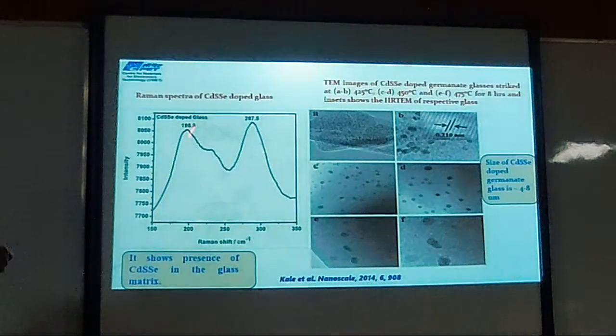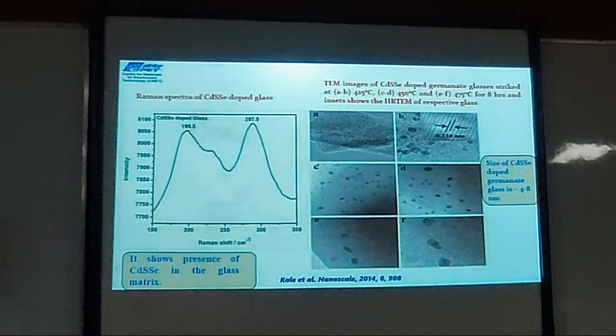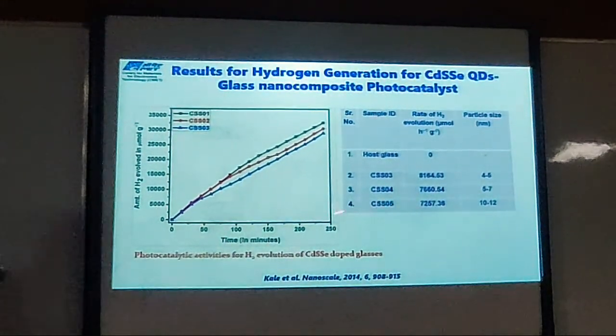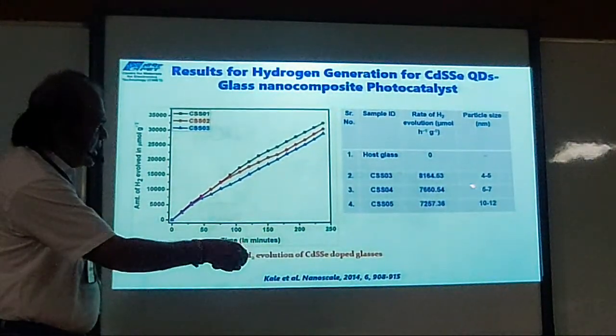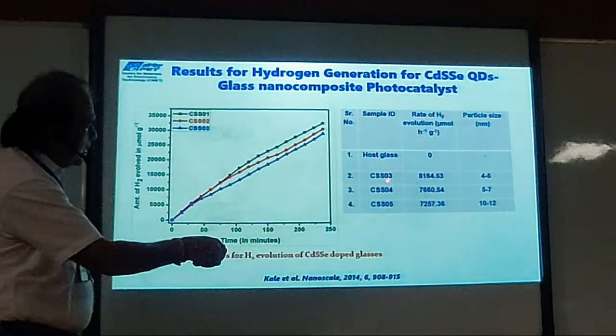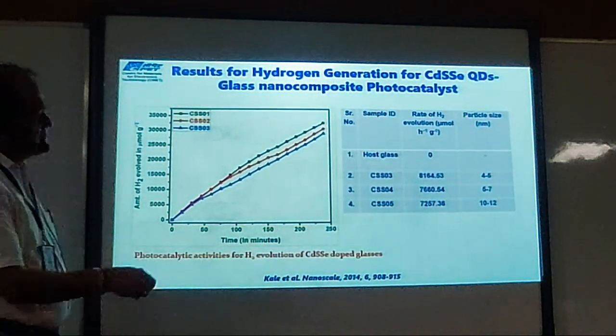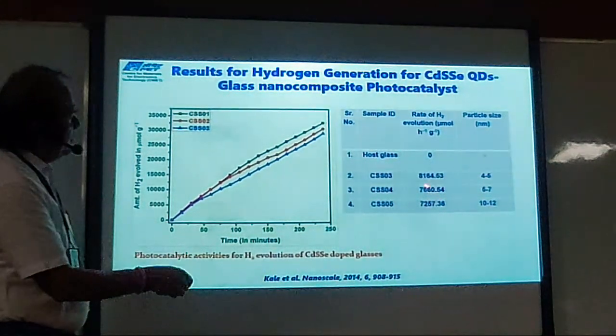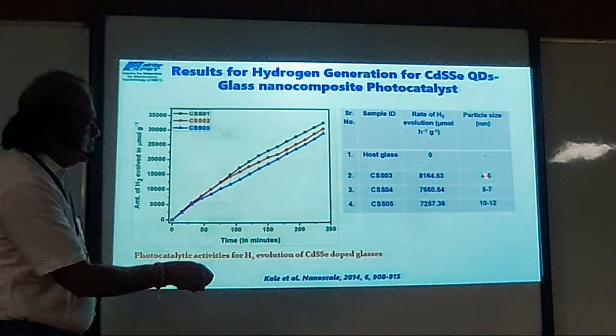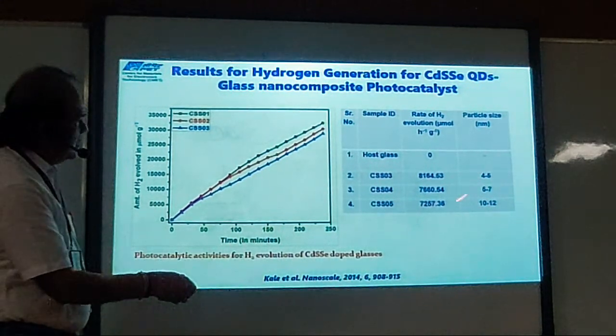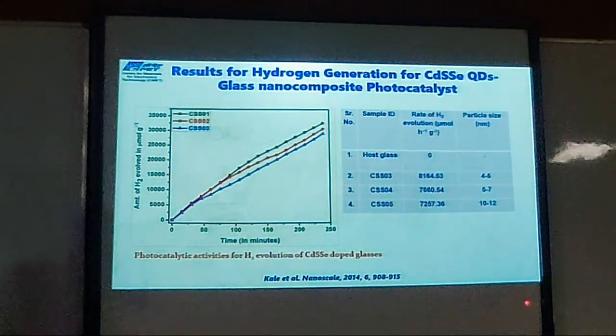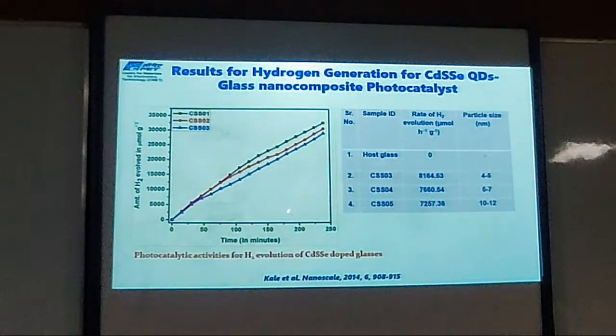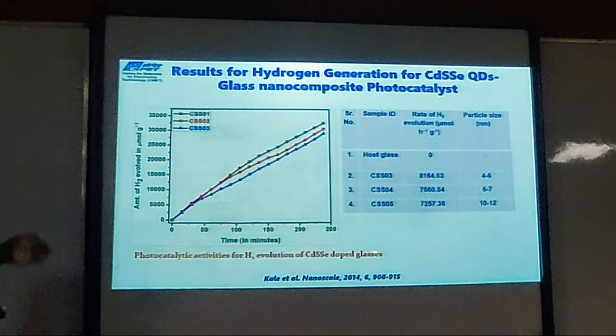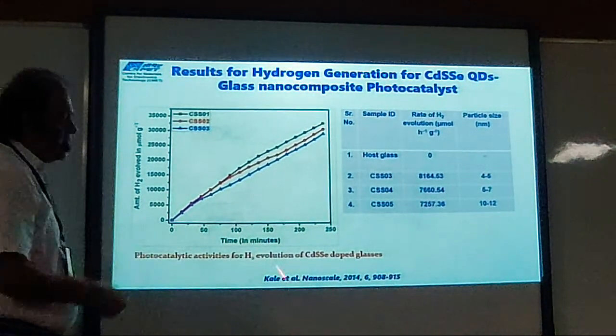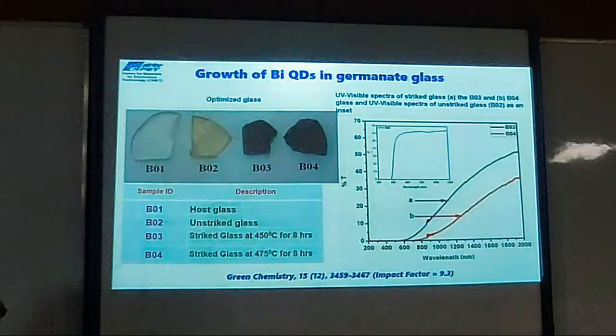So we supported with Raman and TEM. See here, where the quantum dot size is very, very low, 4 to 5 nanometer, we get high hydrogen evolution. So we feel that if we produce 3 to 4 nanometer or 2 to 3 nanometer, this will be enhanced much higher as compared to others. The beauty of this is the regeneration is very, very easy, because you just put in water, rinse it, and put it back again for the catalytic purpose.